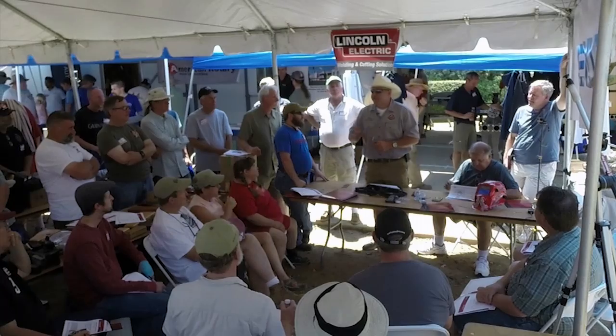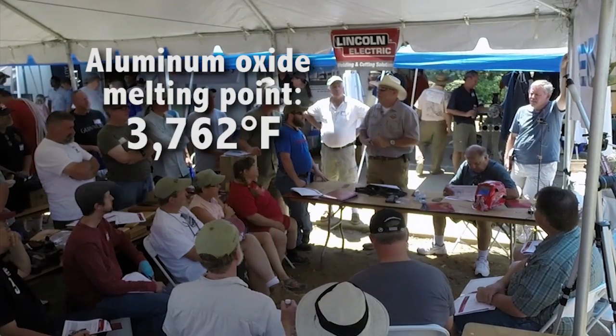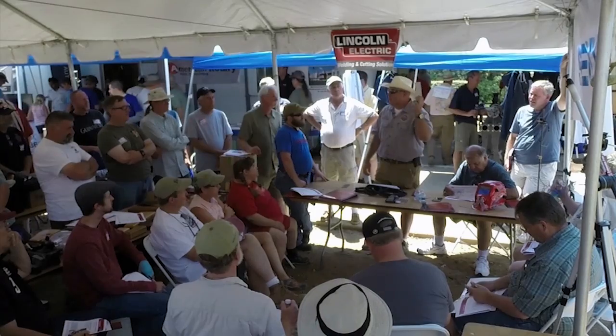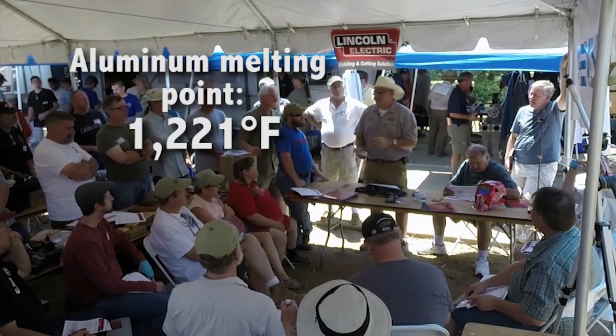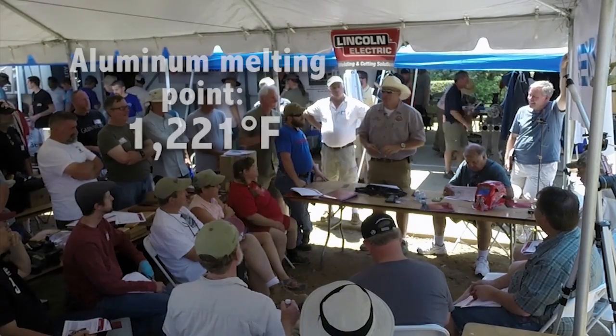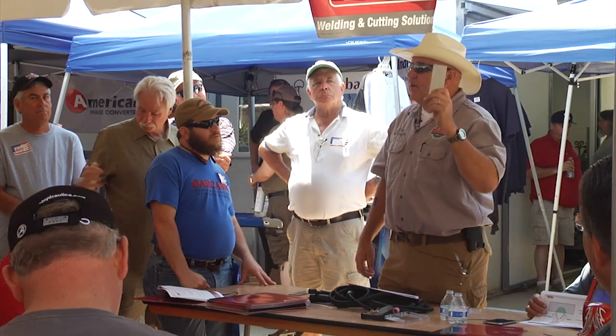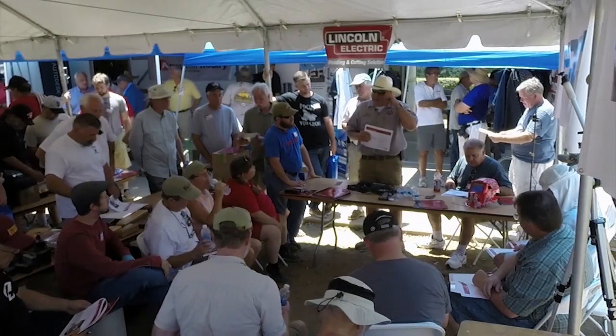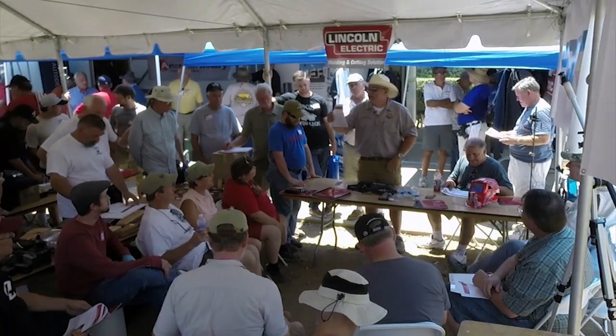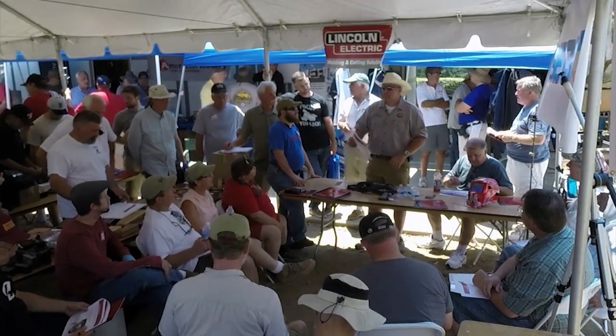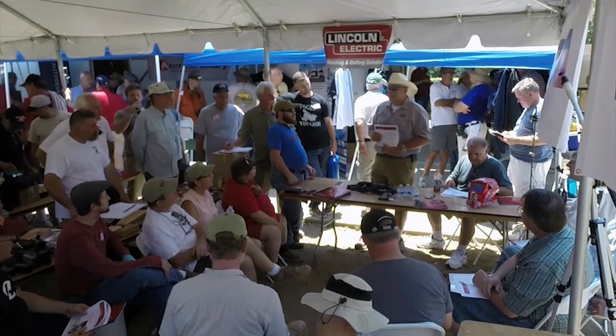That aluminum oxide layer, it melts at about 3,600 degrees. You can write that down if you want to. This aluminum melts at around 1,200. Trust me, it makes the math easier, okay? I'm using round numbers. So about three times hotter to melt the aluminum oxide that forms on the surface. How do we get the oxide layer off the aluminum and weld it?